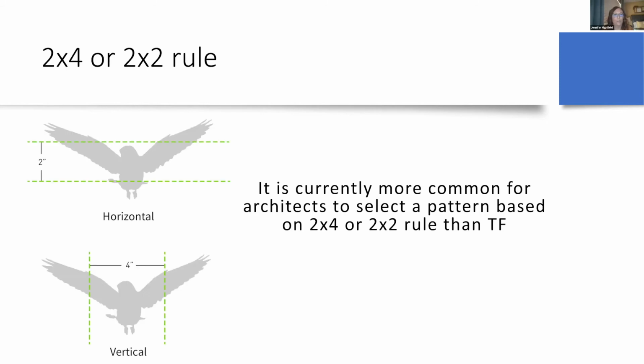The 2x4 rule represents the minimum opening that most migratory birds perceive as passageways, thus preventing them from trying to fly through the glass. While using the 2x4 rule can deter collisions, after additional monitoring, it became evident that reducing the space to 2 inches in both directions may protect small songbirds that will fly through a 4-inch gap. Although the 2x2 spacing is the preferred choice, 2x4 spacing has been demonstrated to reduce collisions significantly and can still receive a bird-friendly rating.